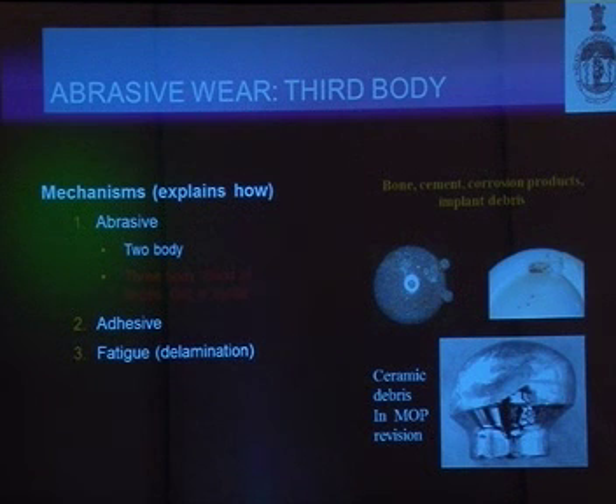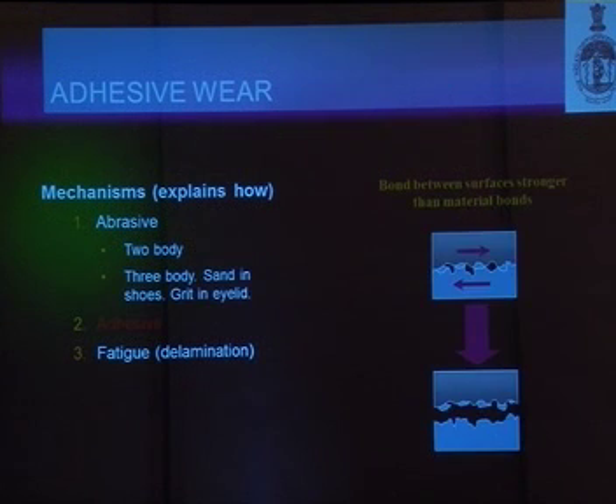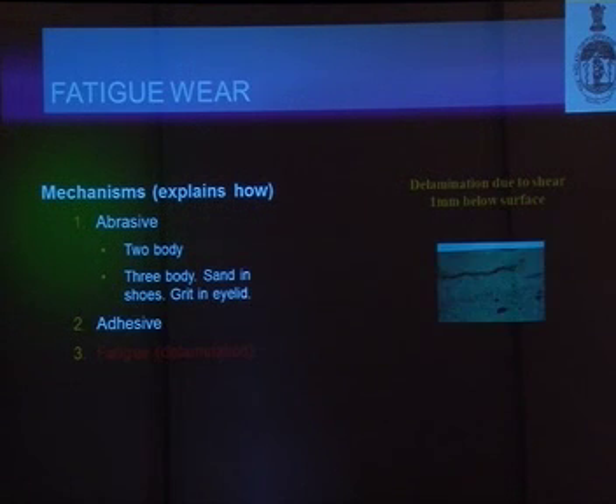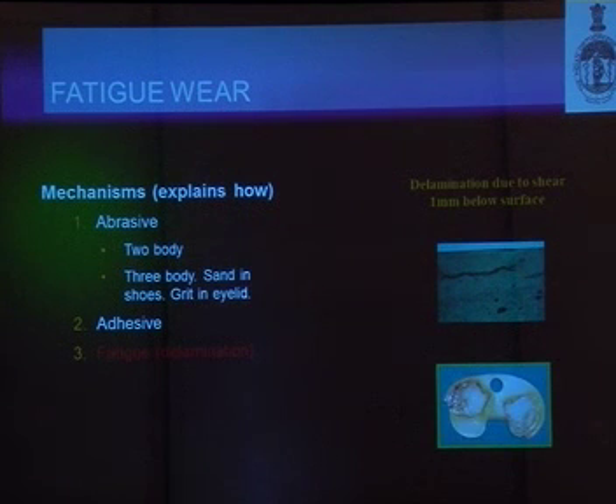This is an example of a ceramic debris in a MOP revision and a poly fracture of the ceramic liner there. This bond between the surface becomes stronger than the material bonds in adhesive wear. And finally, the delamination or the fatigue wear, which normally happens under the surface of the cartilage or of the bearing surface. It results in pitting, delamination, and fractures.